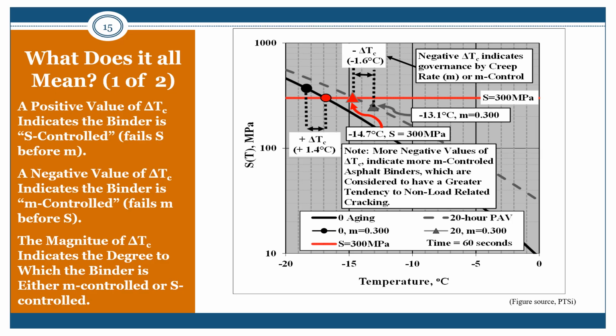The magnitude of the delta TC value, or the absolute value, indicates the degree to which the binder is M controlled or S controlled. In this figure, you can see we have an unaged binder where we have M here and S here, and the delta TC is a positive 1.4 degrees Celsius, which means that the S criteria fails before the M criteria. And here we have this same binder aged 20 hours in a PAV, and now you see that it's reversed. The M value is failing before the S value, and now we have a negative 1.6 degrees separation for the delta TC. Note the more negative values of delta TC indicate more M-controlled asphalt binders, which are considered to have greater tendency to non-load related cracking.